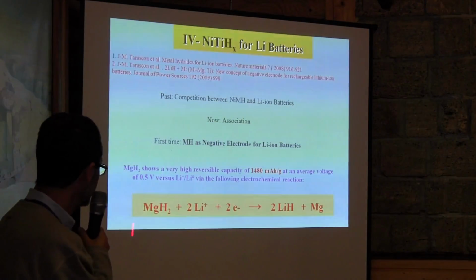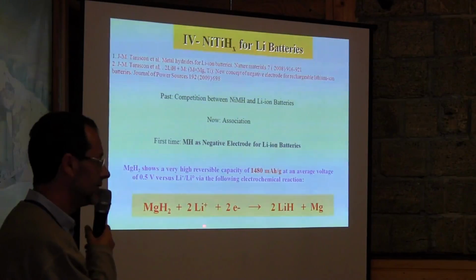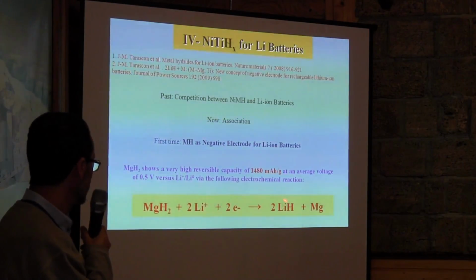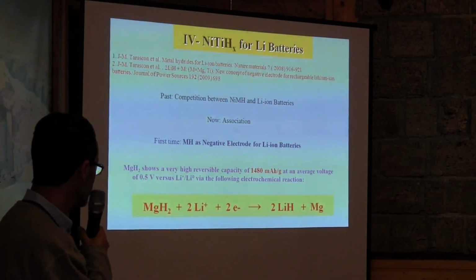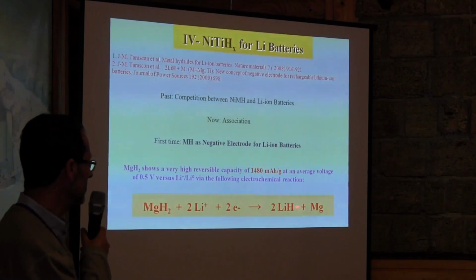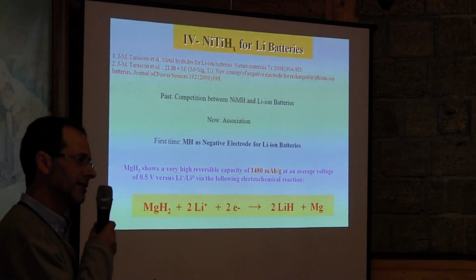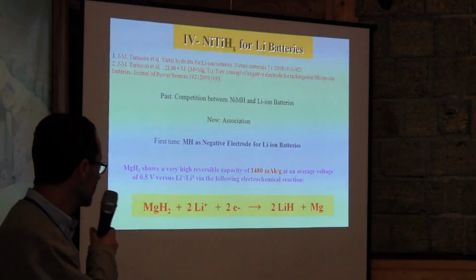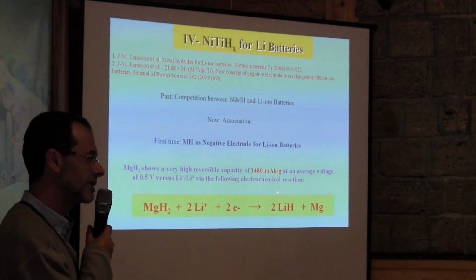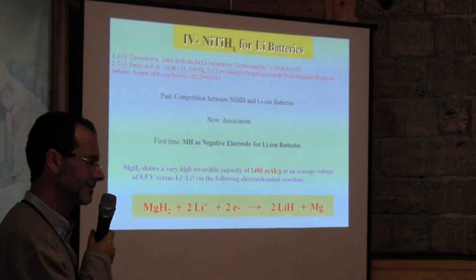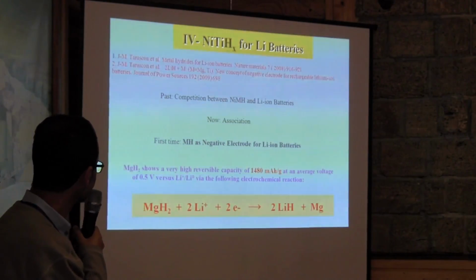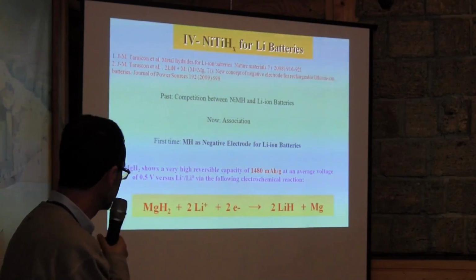Okay, so if you have a magnesium hydride, you have lithium, so hydrogen can be released and interact with lithium, and you have lithium hydride and magnesium. I don't know if people know, but imagine the capacity, how much? 1,500. It's very, very high. And they published this in Nature. Okay, now I worked on this system.